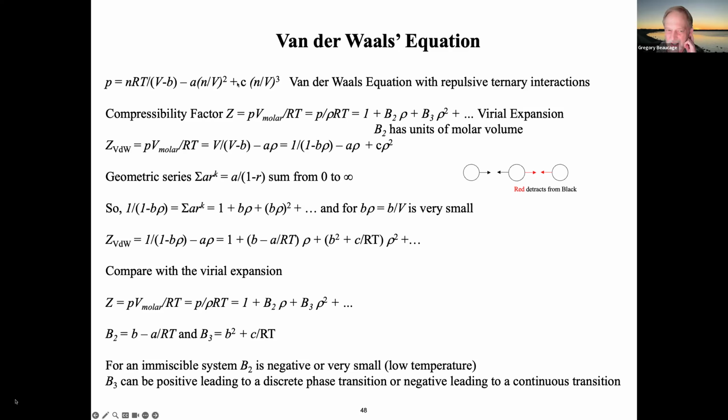If it goes negative, then it does the same thing that A does. It causes phase separation, right? So these things can have signs plus and minus. And when A is 0 without C, that's the critical point. And C is 0 means you don't have ternary interactions. So again, this starts to get kind of complicated, right? Even just adding one term, it becomes a question of what is this thing that you can spend some time thinking about.